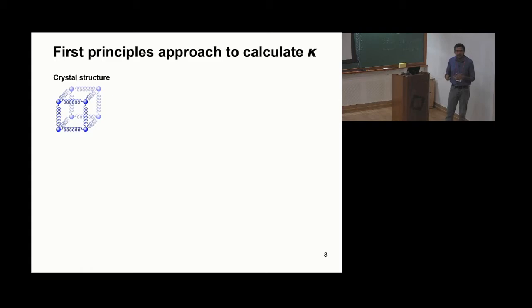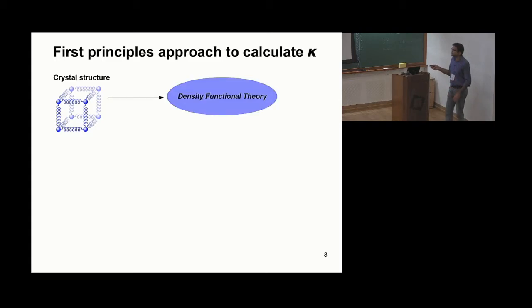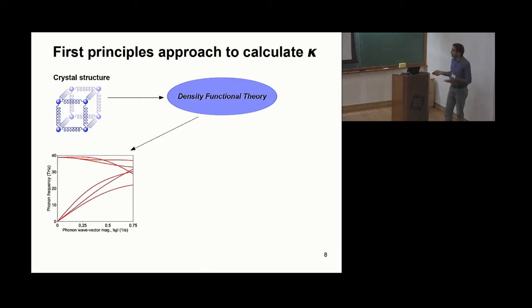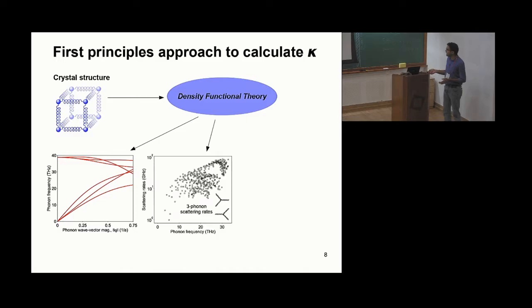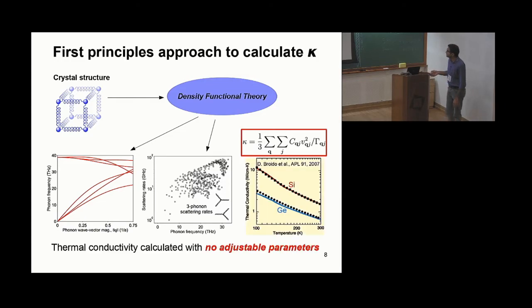That's it. If we just have this information, we can drive it through the density functional theory machinery and calculate properties such as phonon dispersions and scattering rates very accurately for any material, without any adjustable parameters. Once we have these two quantities, we can put this through the kinetic theory expression and calculate the thermal conductivity of any material.